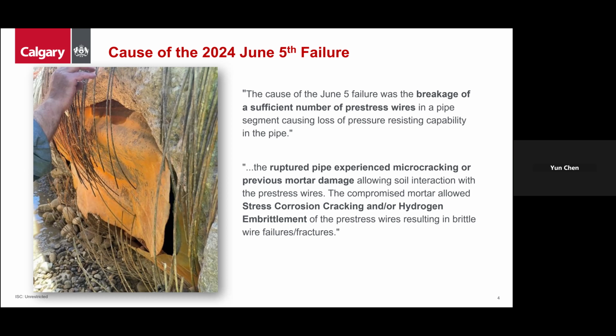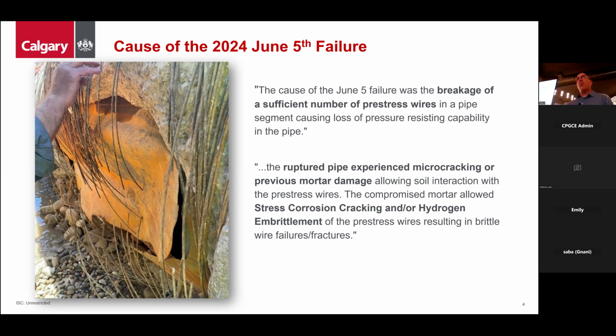The compromised mortar allowed for stress corrosion cracking and/or hydrogen embrittlement of the pre-stressed wires, resulting in brittle wire failures and fractures. In fact, we totaled approximately 200 wires that had failed within the pipe, and there were over 400 wires within an entire 16-foot section. So roughly half of the wires in the pipe had broken within the structure itself.